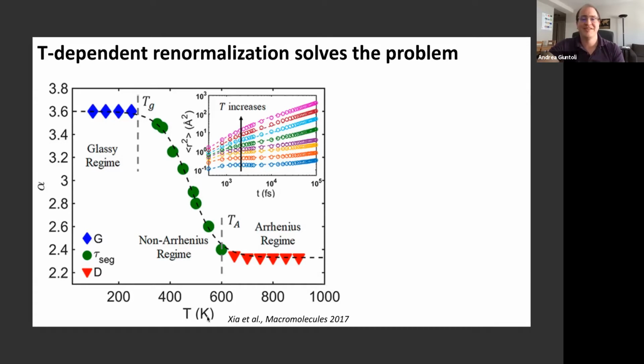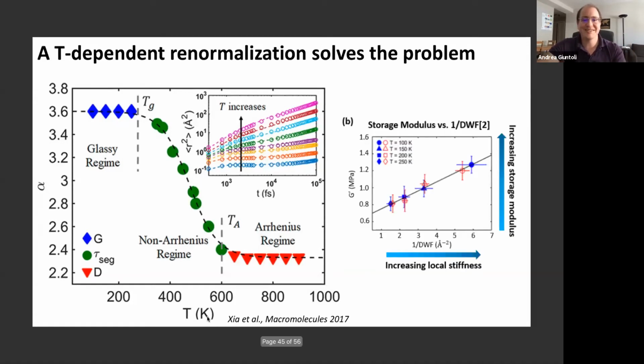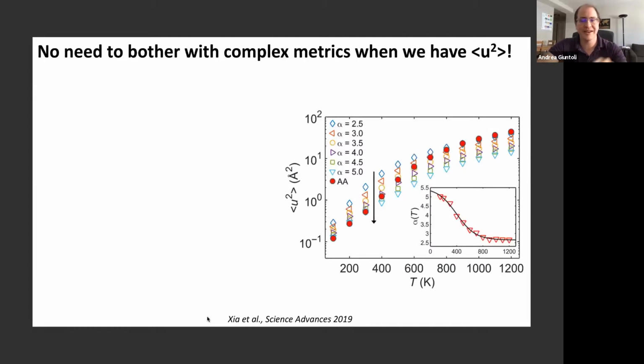We saw that. And they also saw that in this case, the shear modulus was also connected to the Debye-Waller factor, because as we discussed in the Boson Peak case, the Debye-Waller factor is still a measure of the softness of the cage. So it is in fact related to the modulus as well. And so the next step, this was 3 years ago, the next step they did, which is pretty recent, is just to forget about all these complicated metrics and just believe in the power of the Debye-Waller factor.